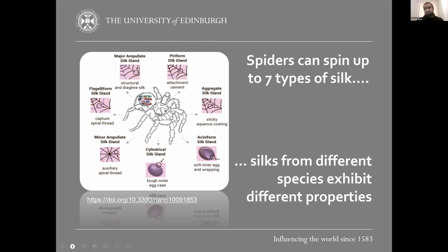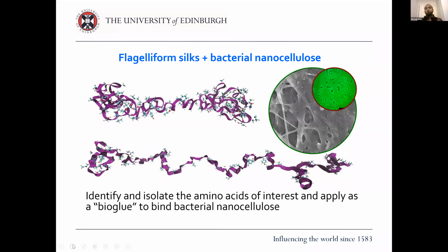This one, when we modeled this silk, we noticed that even though it is not traditionally seen as a bioglue, whereas the piriform and the aggregate gland silks are, this particular silk has a spiral structure that forms a huge number of intramolecular hydrogen bonds. Whereas in the dragline and the tubuliform, you've got intermolecular hydrogen bonds. These ones are intramolecular hydrogen bonds. And so what we thought is that if we were able to identify and isolate the amino acids that are actually responsible for mass hydrogen bonding in the flagelliform silk, we could use monomeric forms of these amino acids as bioglues and apply them to stiff natural biopolymers like nanocellulose.